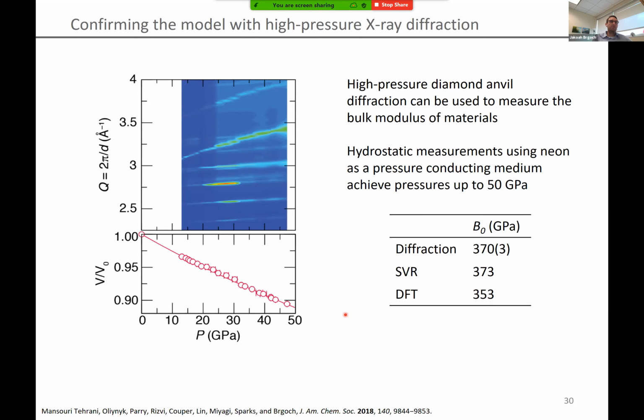Perfect. So what we did was we went ahead and measured the material's bulk modulus. We wanted to make sure that our machine learning predictions were in fact correct. So we went and did high pressure diamond anvil measurements. In this case, you grind up the powder, put it between the diamonds and compress the unit cell.